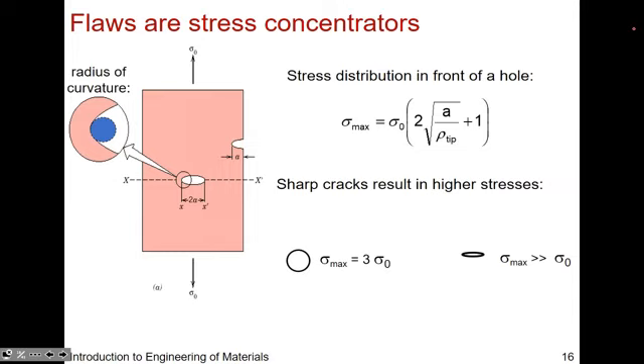So let's talk about stress concentrators. If you have a crack, the mathematical formalism on how to model a crack and how it propagates is with a sphere or a circle in this case. So in 2D here, XY, you see this crack as being representative as a circle. You can have just a nice round circular crack, or you can have a really extreme thin crack, so that's more ovalish. That's the example that you see on the right. Then if you apply some stress, this sigma naught, how is the stress right at the tip of that crack going to be? As the name denotes, it's concentrated. It's a stress concentrator.